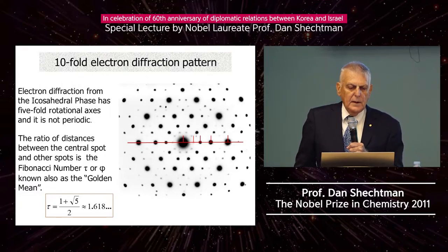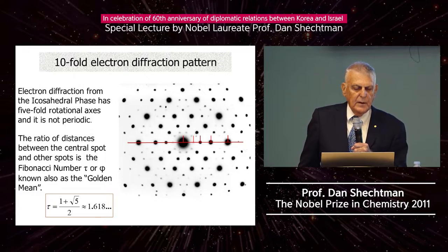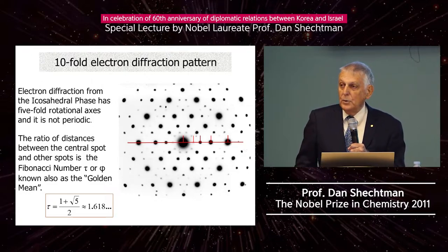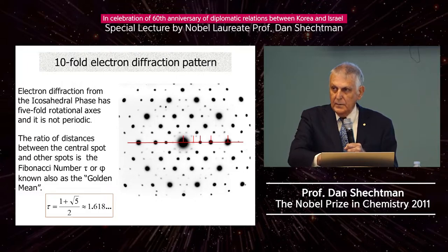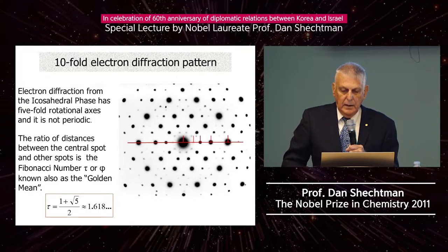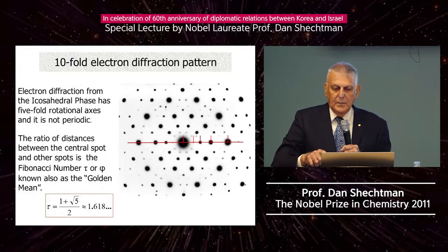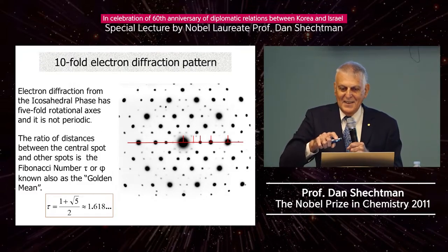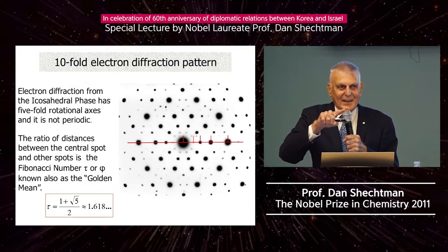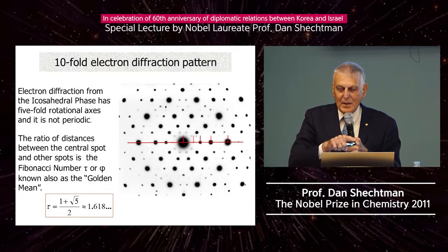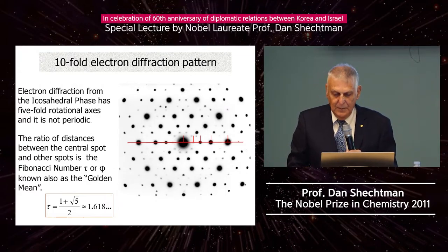So this is electron diffraction from the icosahedral phase. It has a five-fold rotation axis, not tenfold, although it seems ten here. You count them. This is exactly what I did. I started to count them, and I counted 1, 2, 3, 4, 5, 6, 7, 10? No, cannot be. 1, 2, 3, 4, 5, tenfold, and I wrote tenfold in my logbook.